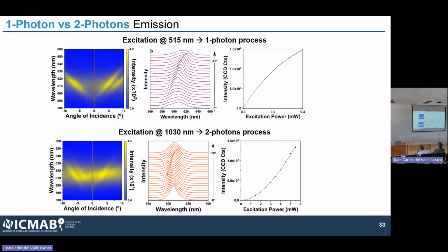While when we put the nanoparticles, we try to compare the 1-photon versus the 2-photon emission system. On the top, you have the 1-photon, so 515 excitation. Very simple: we excite at 515, the quantum dots emit. And this process is mediated by the presence of the metasurface. So as you can see here, there is an angle dependence, so we see a modification of the emission. While when we go to the 1030 excitation, in this case we have a 2-photon process. Again, we see a modulation, and the emission is much sharper.